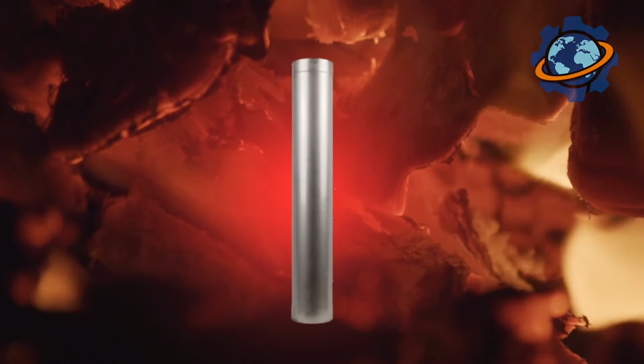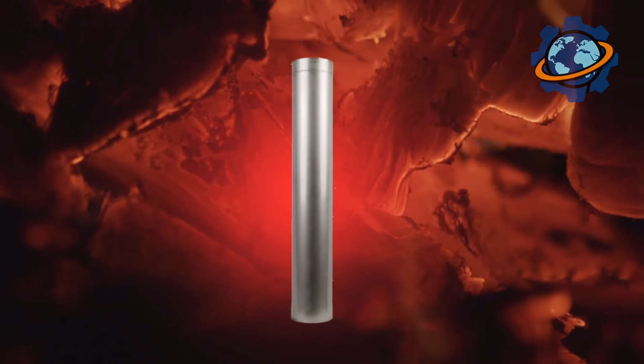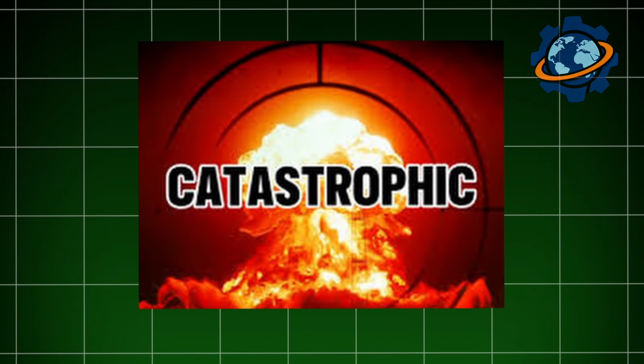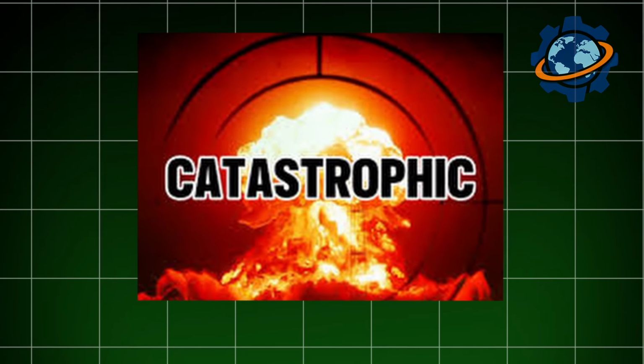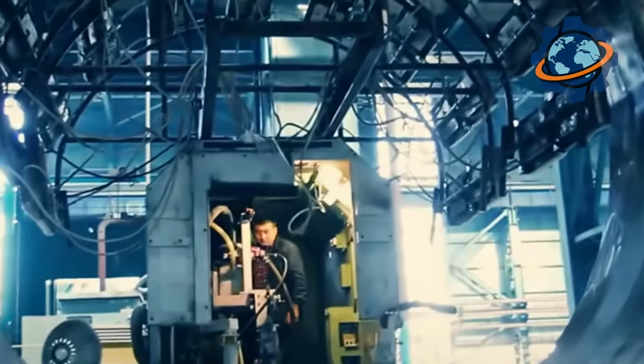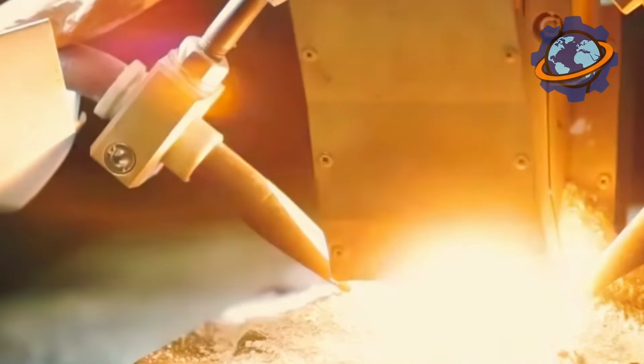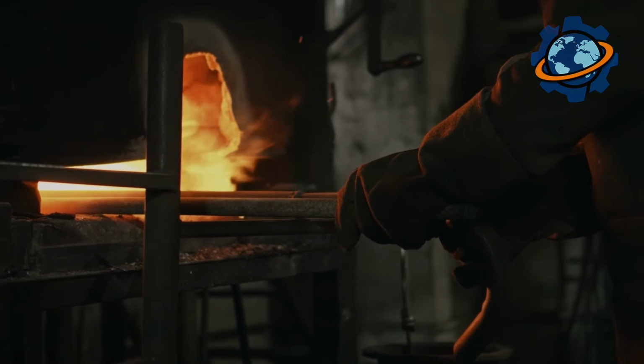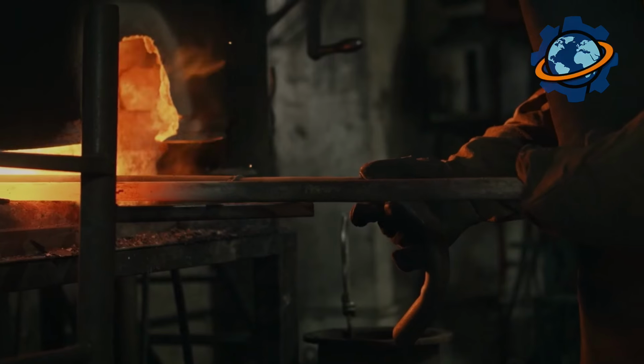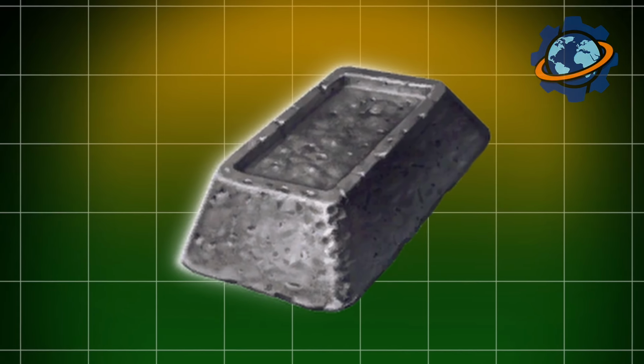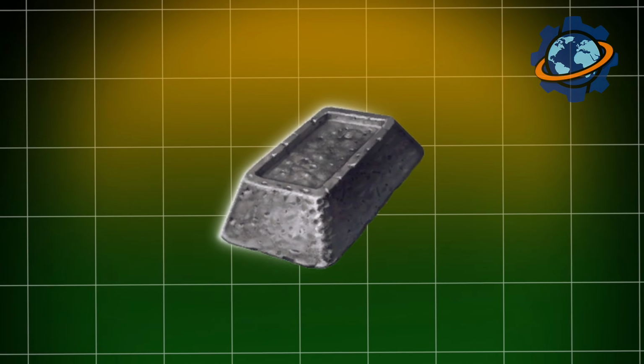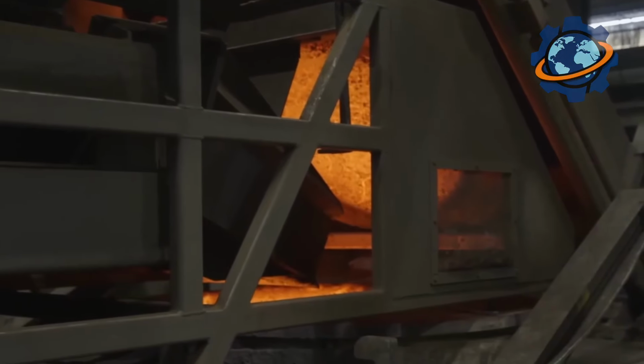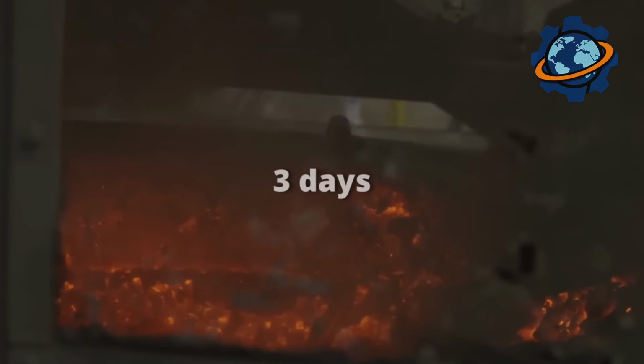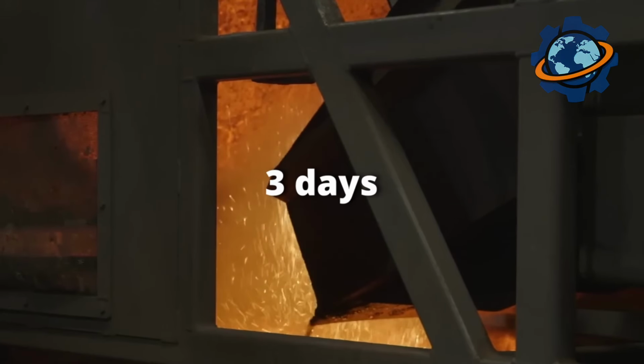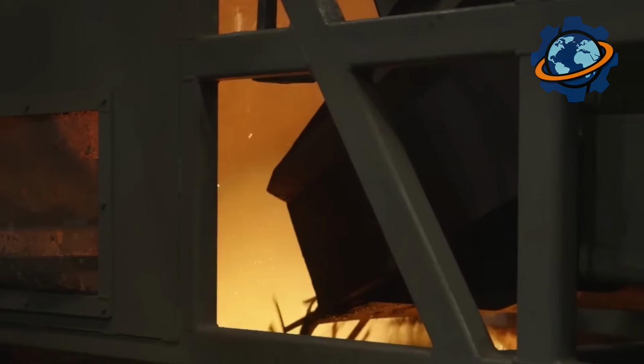Cool too fast, thermal stresses create internal cracks invisible to naked eyes but catastrophic under reactor operation. Cool too slow, large crystals form, weakening the structure. Thermocouples embedded throughout the mold measure temperature at 300 points simultaneously. The ingot shrinks 5 inches in diameter while cooling, enough movement to crack the mold if thermal expansion isn't calculated precisely. Workers strip the mold after 3 days, revealing a steel cylinder glowing dull red at 800 degrees.